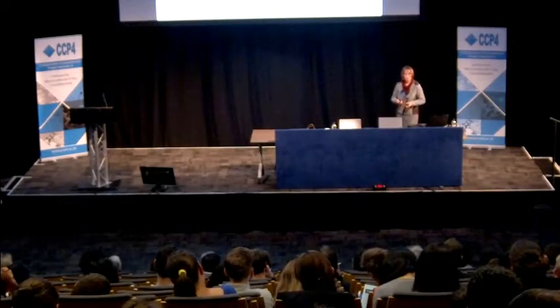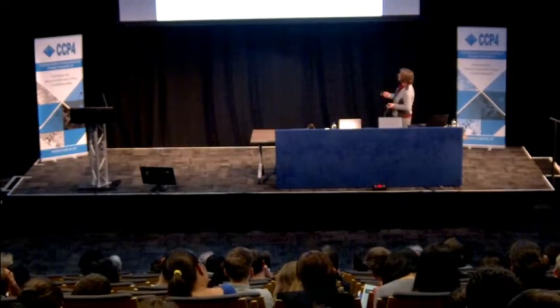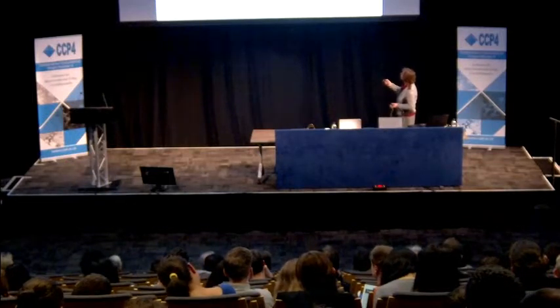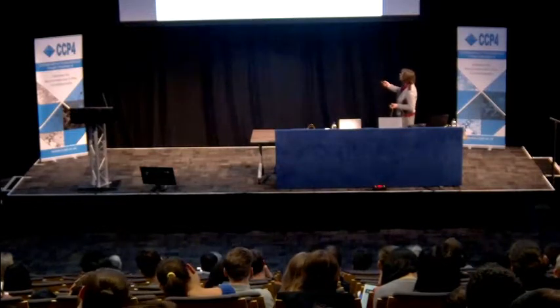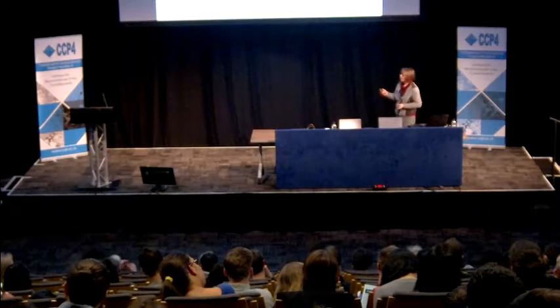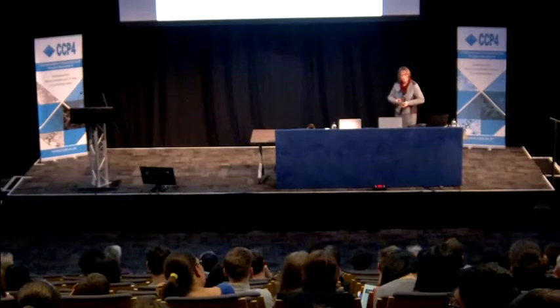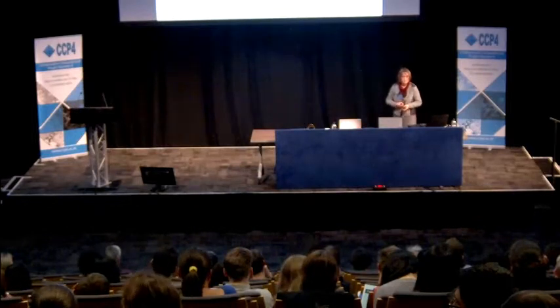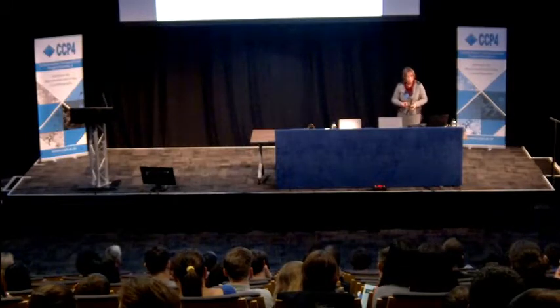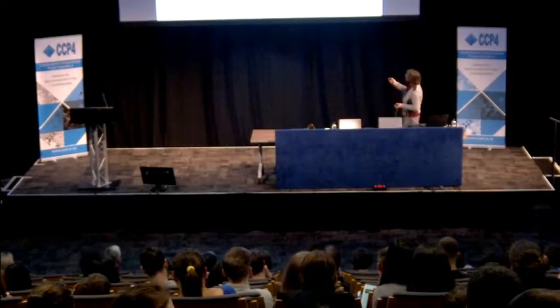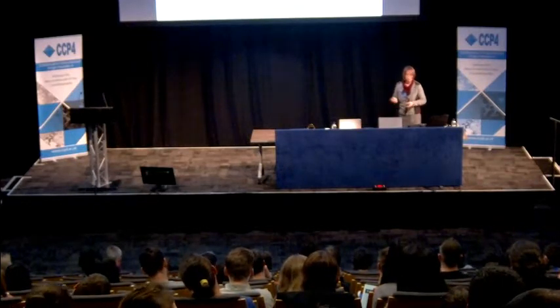On the other hand, we know the orientation matrix of the red domain. So we know the position of the red reflection, and if we have an overlap of the two integration boxes, we can then integrate this whole box, leading to a sum of two intensities. Now we only have two kinds of reflections: non-overlapped reflections and overlapped reflections, and it doesn't matter if the overlap is exact or partial.